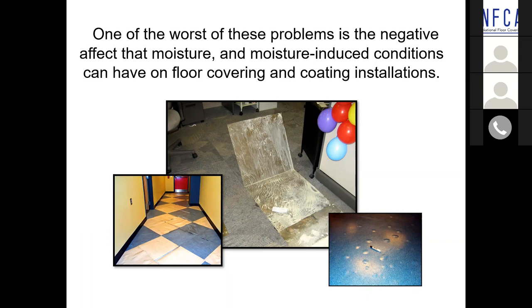Sometimes you start to see indents. Sometimes we begin to see wheel marks. In worst case scenarios, you actually can come back and you can see the arc of the notch trowel coming through the flooring because the adhesive never achieved the degree of set that it was intended to. And the bottom right picture is an epoxy floor. It's not only the coating of the flooring, floor materials or flooring industry that's experiencing problems. The polymer industry, people who manufacture and install epoxy floors, urethane floors, methyl methacrylate floors, are having very similar issues with moisture.